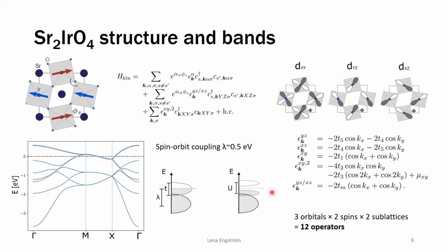And from some DFT measurements that we are using, they can in the same way fit these different hoppings, but we then have to include hoppings in different directions and between different orbitals. We also want to have this rotation included. However, the main thing about the iridates is that we have this strong spin-orbit coupling, and that's where it gets interesting, because then we can actually split out a few of the bands from the rest with a magnitude proportional to the spin-orbit coupling. This means that we have some bands here closer to the Fermi surface, and this effective model describes them pretty closely at higher spin-orbit coupling.